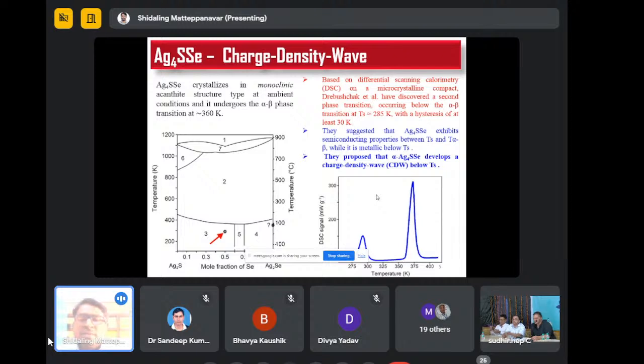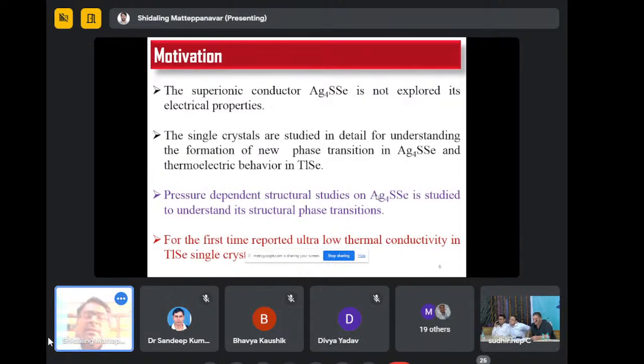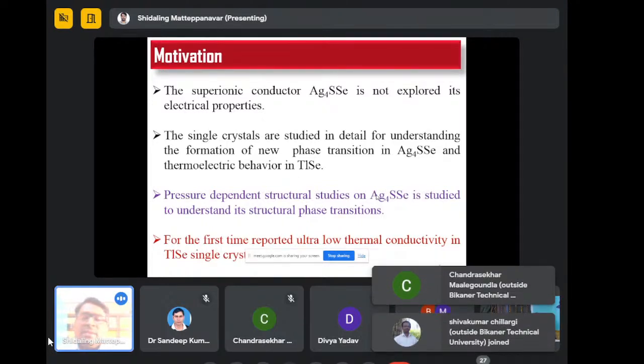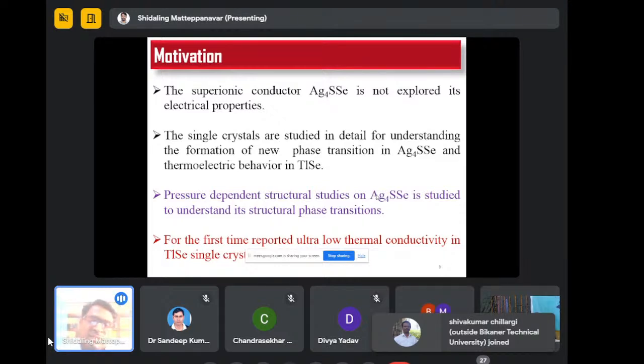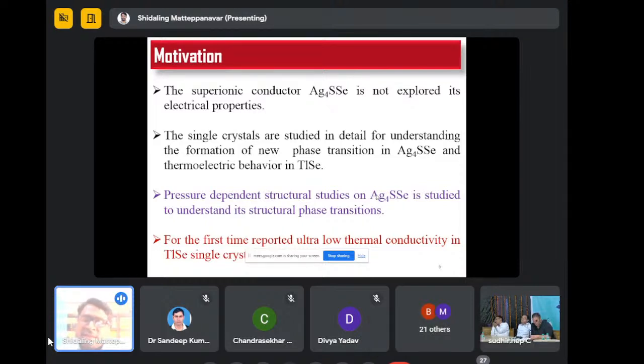With that motivation, we prepared this sample as a single crystal by the chemical vapor transport method. Then we explored the structure around that transition, to see what kind of structural transition is happening. We then went to detailed electrical and magnetic properties and came up with interesting new physics which was not explored earlier on this sample. We also studied the pressure dependent structure of the sample. Later I will come to how this sample can exhibit low thermal conductivity, particularly in the thallium selenide single crystal.